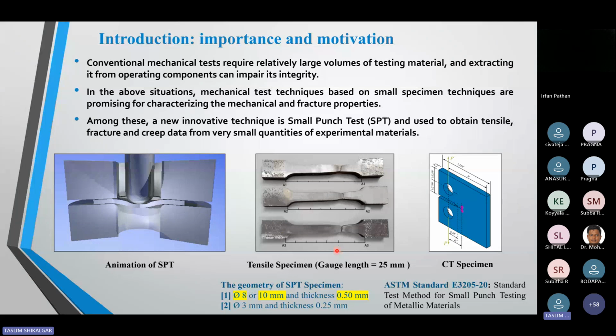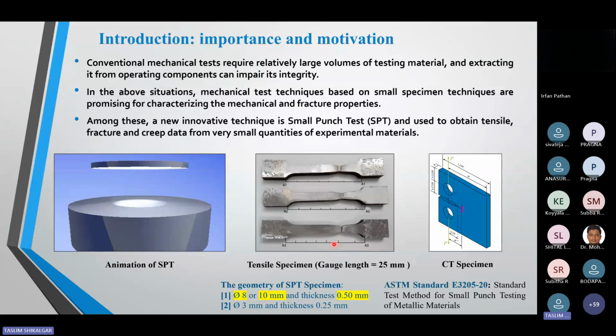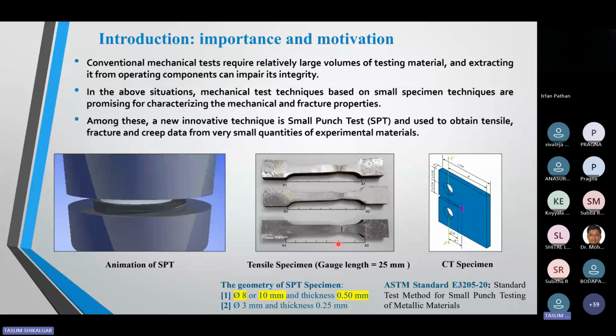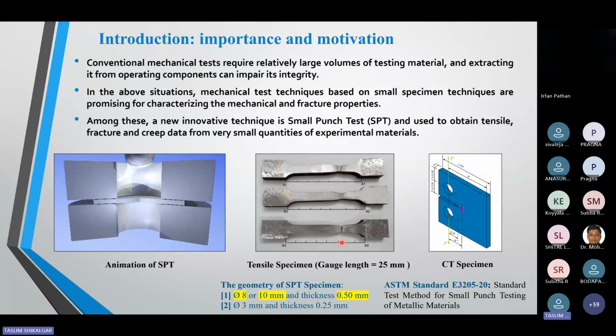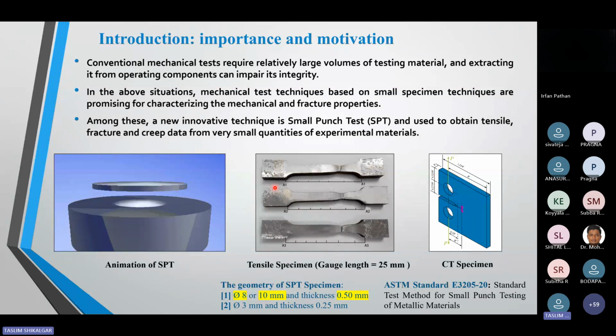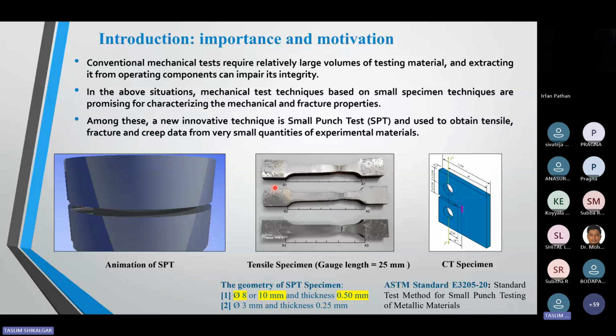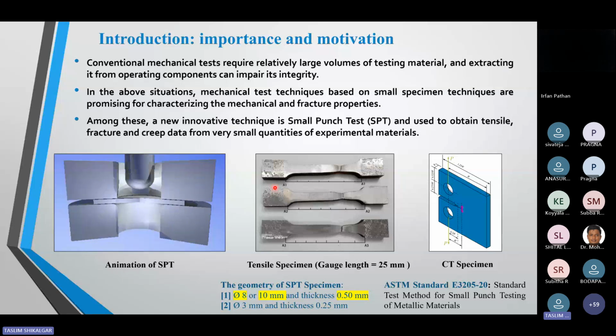Here you can see these tensile specimens. This one has a gauge length of 25 mm. I just want to show this comparison. If we use that much material to get the tensile properties, compared to that, SPT specimens can be manufactured from this type of specimen. More than 100 specimens you can fabricate, test, and generate a parametric study based on these specimens.